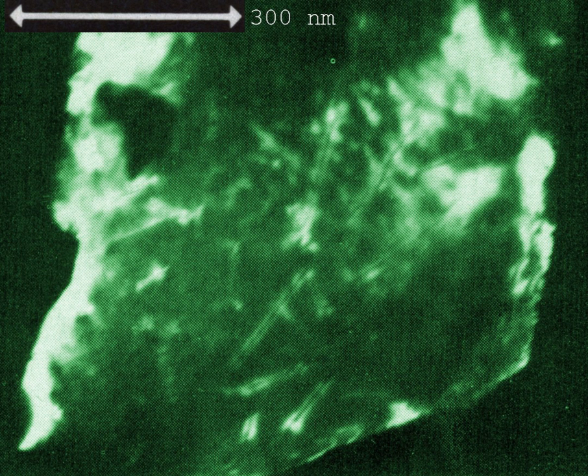According to the thermal spike model, the electron collision cascade is responsible for the energy transfer between the projectile ion and the target nuclei. If the temperature exceeds the melting temperature of the target substance, a liquid is formed. The rapid quenching leaves behind an amorphous state with decreased density. Its disorder corresponds to the ion track. The thermal spike model suggests the radiation sensitivity of different materials depends on their thermal conductivity and their melting temperature.